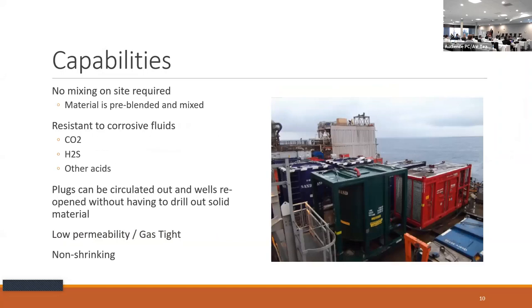The good news is you don't have to mix it on site. And the bad news is you have to bring it all out there and shear it before you actually pump it into a well. So that's a bit of a challenge. Another great advantage of the system is it's not calcium silicate. So guess what? You can put CO2 next to it. You can put H2S next to it, and it's not going to corrode away or go away.